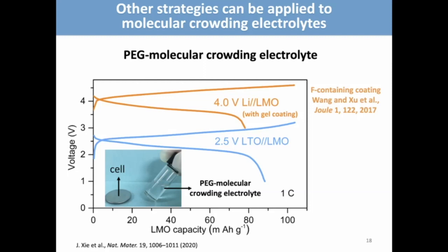So what we compared so far is based on a pure electrolyte system against other highly concentrated electrolytes. But we also know that there are other strategies that have been developed in water-in-salt type electrolytes, such as gel coating. So we also apply the coating developed by Professor Wang and Professor Xu, a fluorinated coating, to enable a 4-volt full cell using the PEG molecular crowding electrolyte. So this is just a starting point for a pure electrolyte system, to which we can even add other types of strategy to make it better.